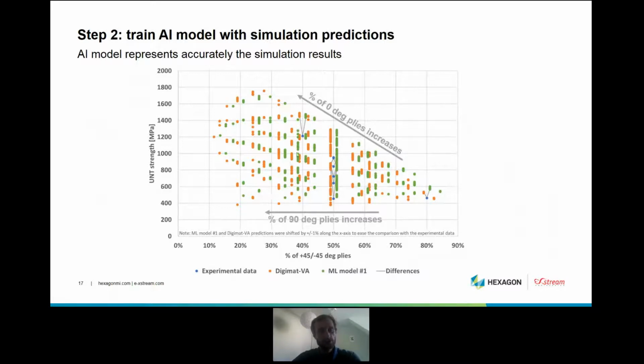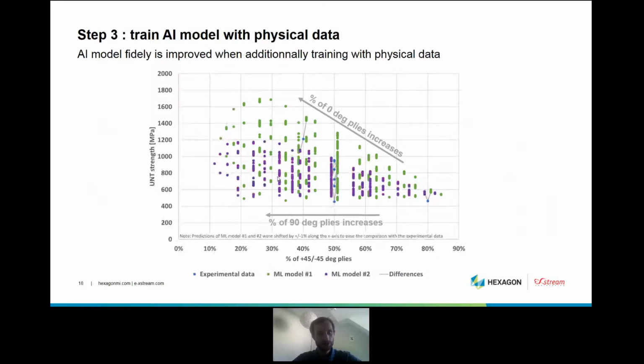Okay, so what you see on this graph is only the case of unnotched tension strengths for the different kinds of stacking sequences. The orange points are simulation results, and the green points are what the trained AI model is able to predict. And so what you see is that an AI model is able to replicate pretty well what you get from the simulation. But at this stage, what we haven't done yet is include the value of the experimental data. And so this is actually the next step.